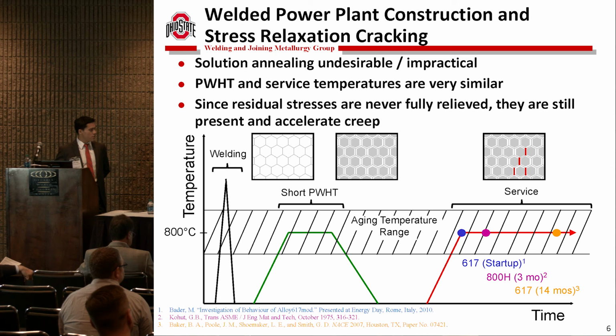You can imagine also that if the grains were larger, there would be less grain boundary area, and the alloy would be more susceptible to cracking. Unfortunately, what you want for creep resistance is larger grains, but that also makes you more susceptible to a phenomenon like relaxation cracking.